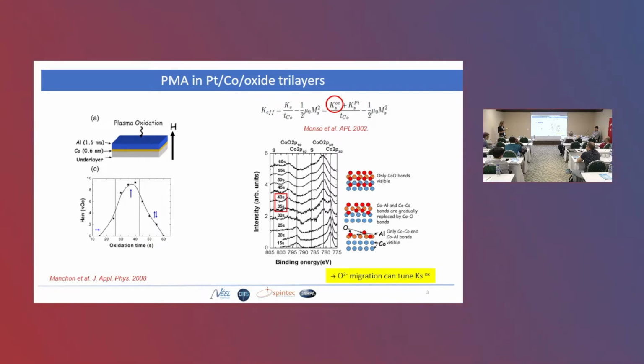And what we showed by XPS measurements is that this maximum anisotropy corresponds to the situation in which the cobalt-aluminum and cobalt-cobalt bonds are totally substituted by cobalt-oxygen bonds. So in this position, the last cobalt layer is totally covered by oxygen. In this case, we understand why the oxygen migration induced by electric field can change the anisotropy.